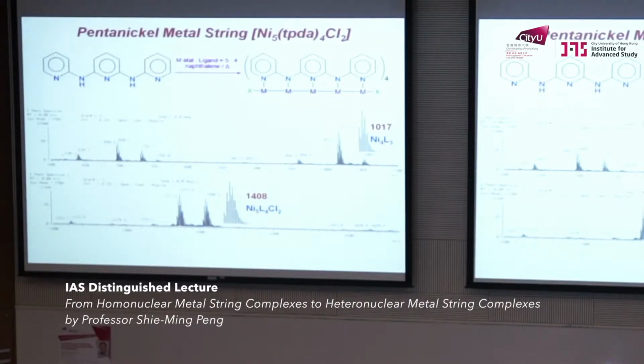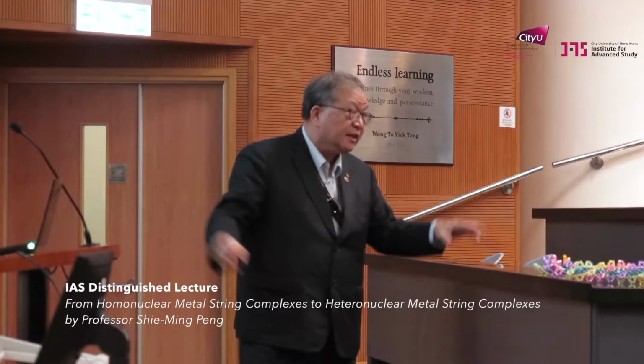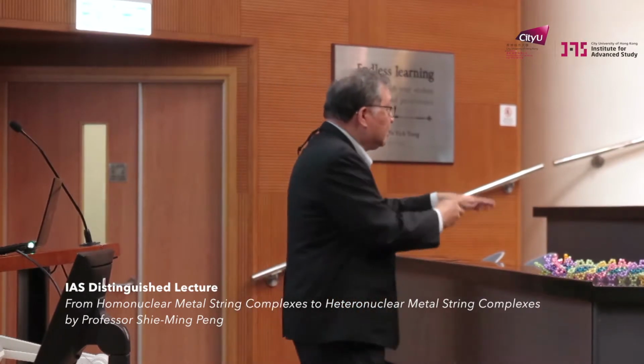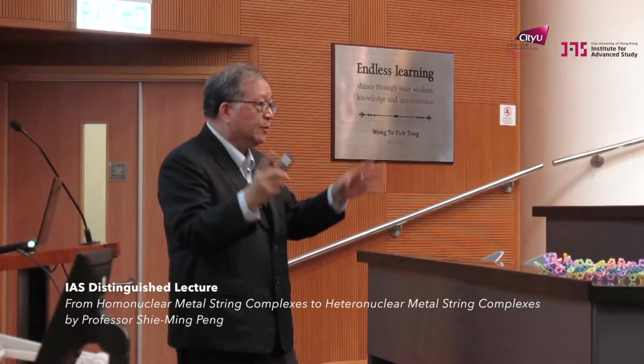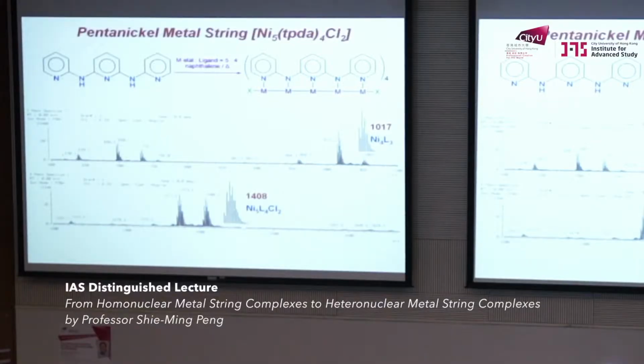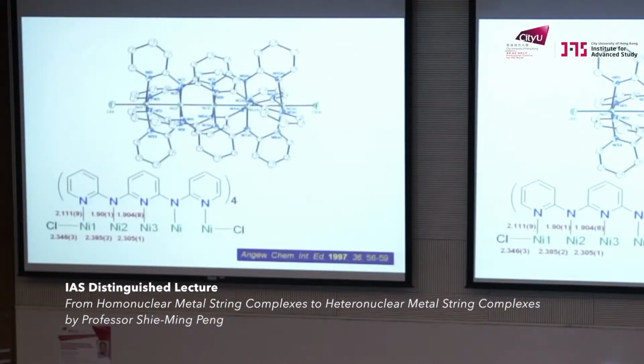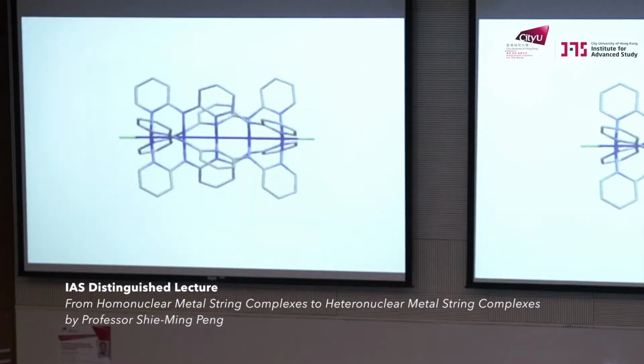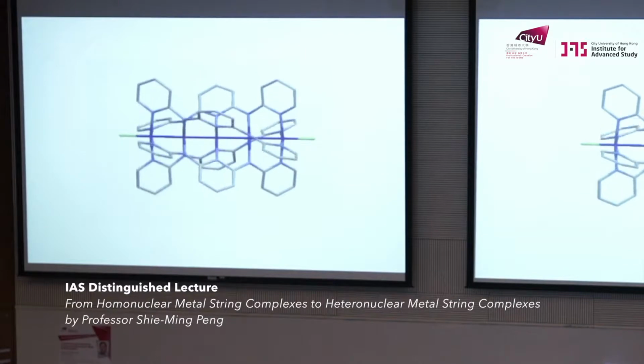It's very diagnostic because nickel has isotopes, chlorine has isotopes. This is the parent peak of this composition, and this is the experimental. This is the simulated one. It's like a fingerprint, okay? Because you have so many isotopes, then you have the fingerprint. And when we simulated this one, I just jumped up because it fit so well. Of course, we got the crystal structure of this pentanickel system, and the inner nickels are low spin, the outer nickels are high spin, and this is the crystal structure of that.